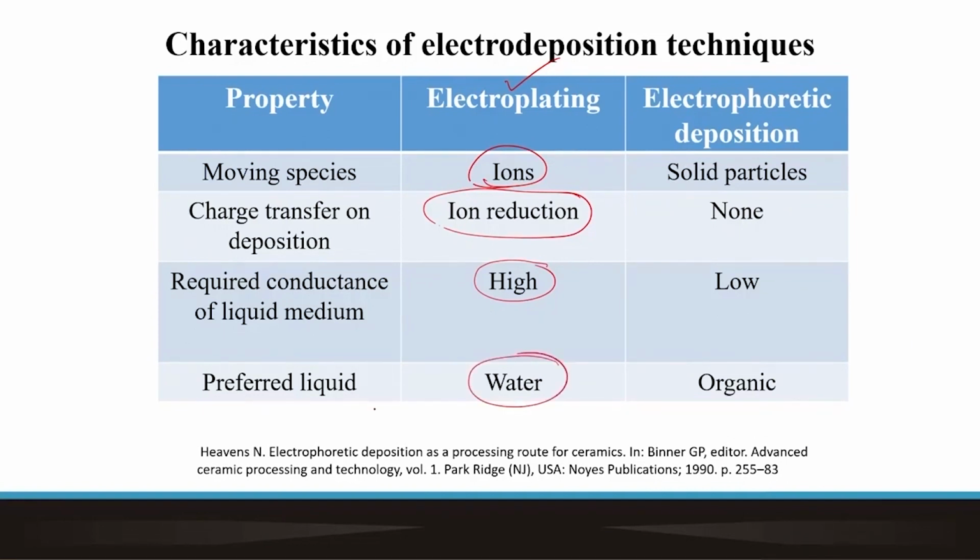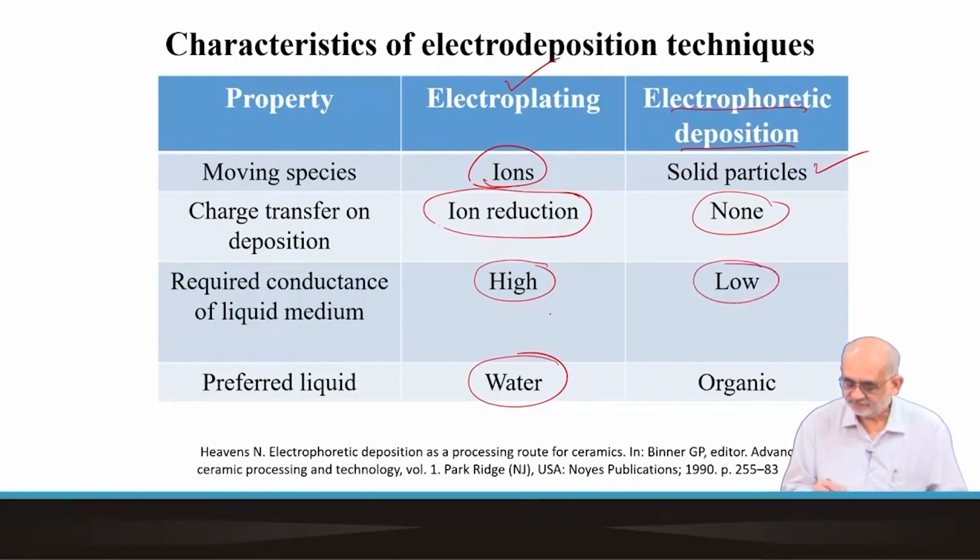In contrast, for electrophoretic deposition, we are talking about solid particles of certain diameter, usually very ultrafine particles. There is no charge transfer involved, though we have a surface charge layer, but those are not part of the deposition process. The medium can be not completely insulating, but may have low conductivity. And instead of water, we can use organic medium or polymeric medium, or typically a dispersion.